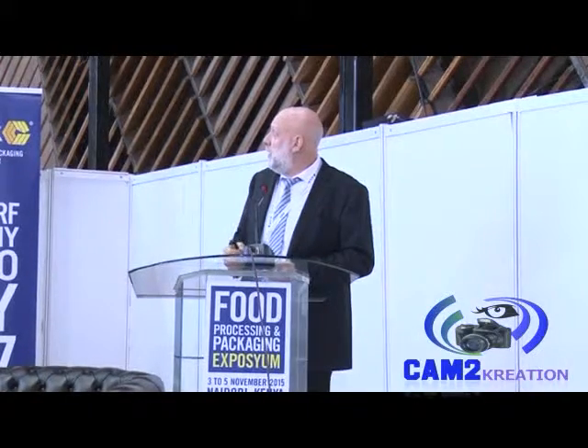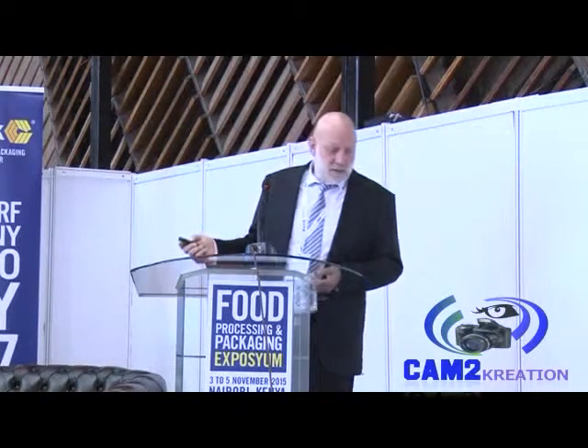The next function of a tie layer in the structure can be explained with this example. If you think about two bricks and you put concrete in between and you move it, it will simply break. If you put rubber in between and you move it, it will be much more flexible. The rubber will absorb the energy which you create during the movement of the layers against each other. This is what the tie layer is doing. And you see that the more tie layer you have in the middle, the more you can move the layers. I will talk later about the necessary thickness of the tie layer in the structure.